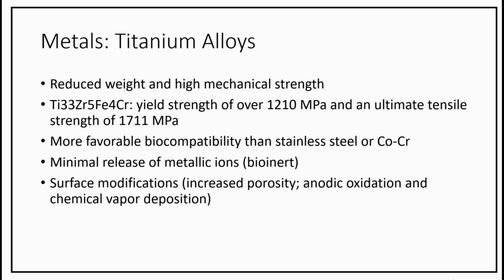Titanium alloys are among the newer biomaterials on the market and have gained popularity due to their reduced weight and high mechanical strength. Newer titanium-based alloys, such as Ti33Zr5Fe4Cr, show a yield strength of over 1,210 MPa and an ultimate tensile strength of 1,711 MPa. In terms of biocompatibility, titanium is more favorable than stainless steel or cobalt-chromium implants since it displays only minimal release of metallic ions, leading many researchers to deem it a bioinert material.